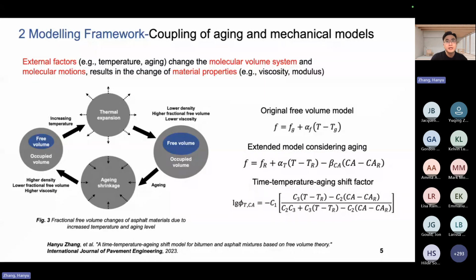Now we are able to model aging, then we need to figure out a way to couple aging with our mechanical models, with the mechanical analysis. So for our project, I developed this time, temperature, and aging shift model based on the free volume theory. And this theory tells us that all the external factors like temperature, aging, solvent, concentration, are all changing the molecular volume system and the molecular motions, and it changes the macroscopic material properties like the viscosities and modulus.